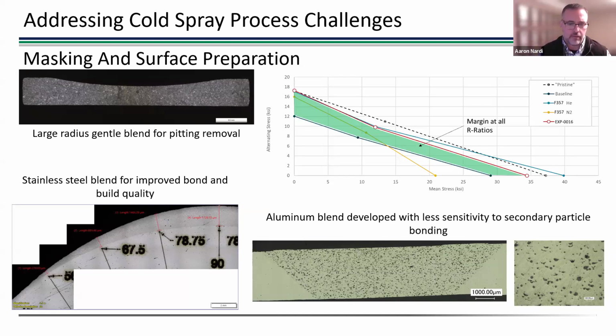And the same thing with this aluminum deposit you see on the bottom right. We've got a very sharp geometry that we're spraying into, and we still get very good quality. All those black dots are actually ceramic particles that are inside of that aluminum, and they're meant to be part of the deposit.